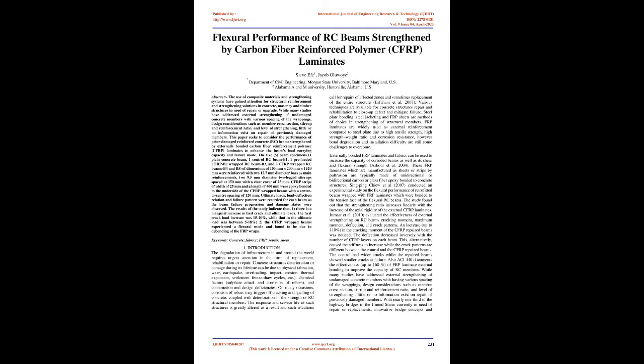1. There is a marginal increase in first crack and ultimate loads. The first crack load increase was 15 to 40%, while that in the ultimate load was between 5 to 18%.